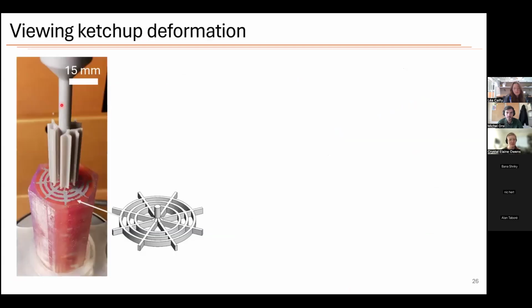And so this is something that we did. We have a cup of ketchup here. This is in a smooth-walled 3D printed container, and I took a little stamp to put a target pattern on here so we can see much more easily what is happening when it deforms. And so again, we have the radius of the vane, and then as the vane rotates, it will cause material to yield out to a yield radius, Ry.